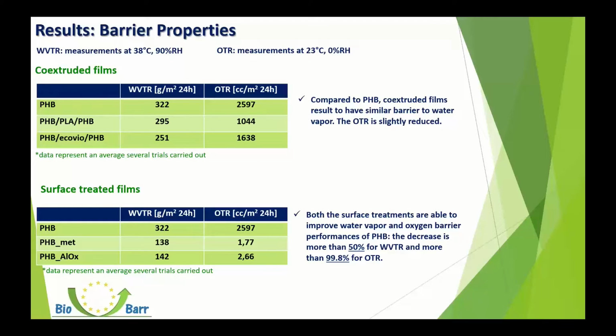Instead, in the case of surface-treated films, both the surface treatments are able to improve water vapor and oxygen barrier performances of PHB, as the decrease for water vapor transmission rate is more than 50%, and in the case of oxygen transmission rate, the decrease is more than 99%.